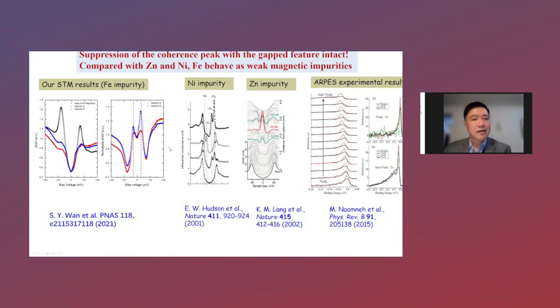Okay, so here I also compare to nickel and zinc doping. The iron doping somehow only suppresses the phase coherence, the coherence peak, but does not change the gap too much.